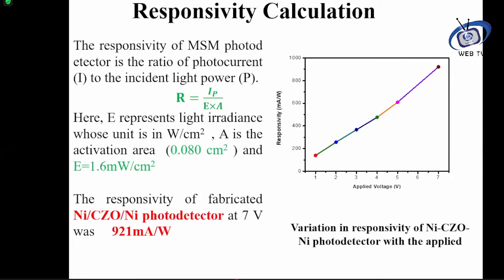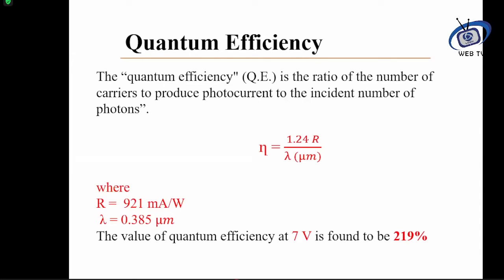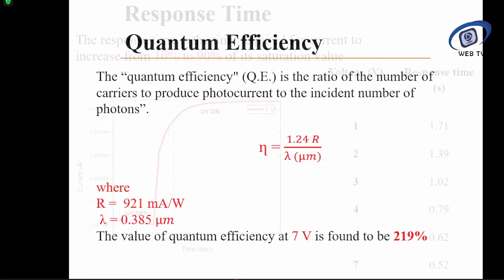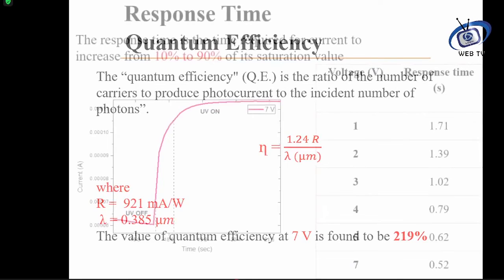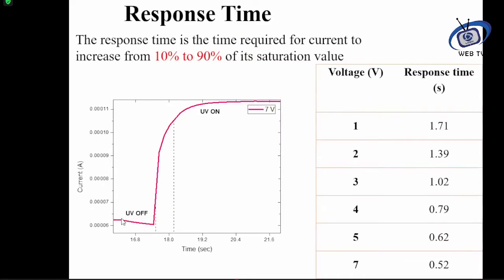compared to other results. And we have checked the quantum efficiency as well by using this formula, which is 1.24 R over lambda, where lambda is the wavelength of the UV light. The value of the quantum efficiency at 7 volt is 219%, which is again very significant. And then we check the response time. When UV light is not present, the current is 60 microampere, and when we turn on the light, suddenly the current has increased.